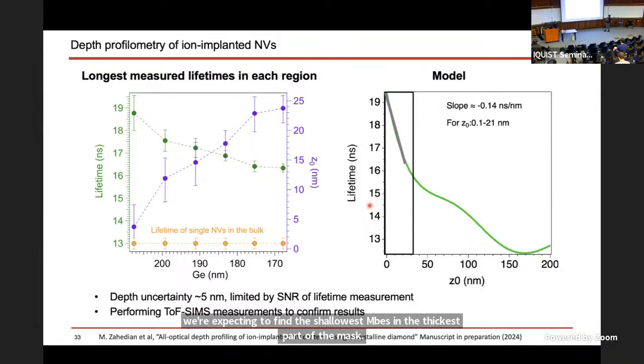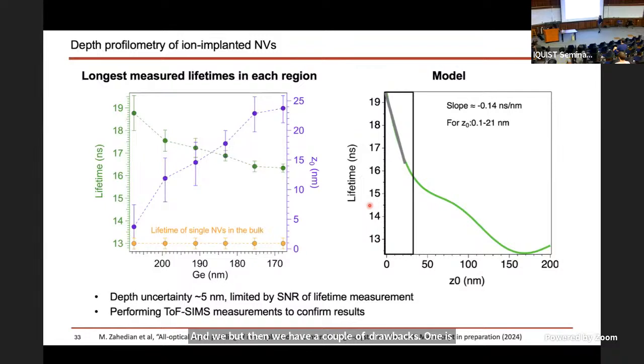But then we have a couple of drawbacks. One is right now our depth uncertainty is actually relatively large. It's at 5 nanometers, limited by the way that we're doing the measurement. And then we need an independent verification. So we're actually performing TOF-SIMS measurements right now to verify our data.